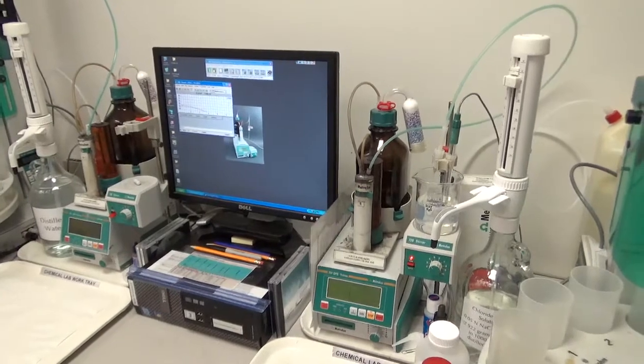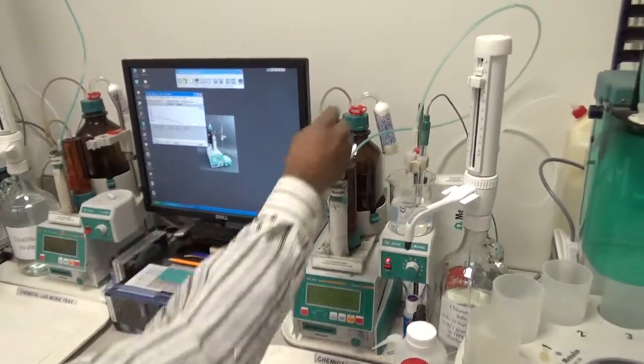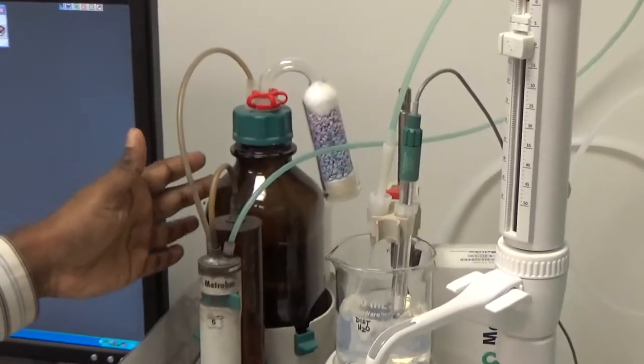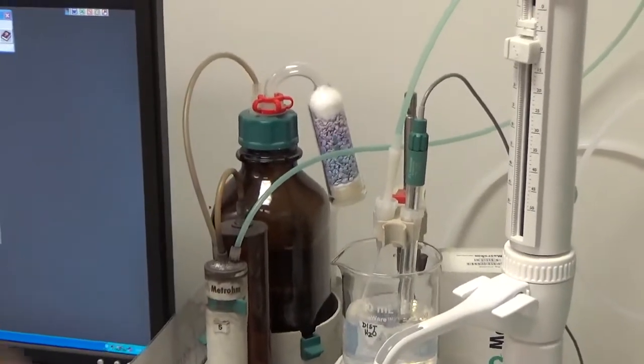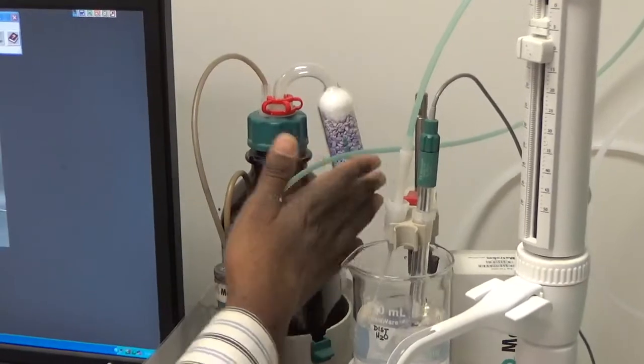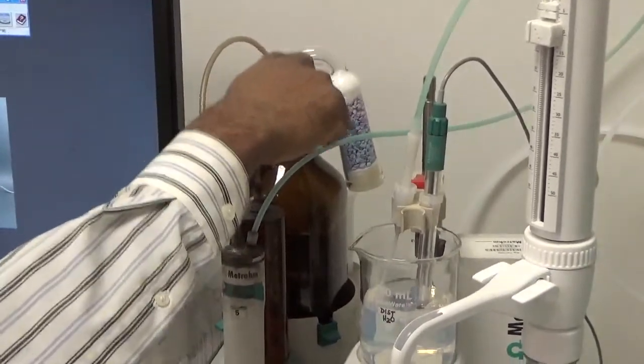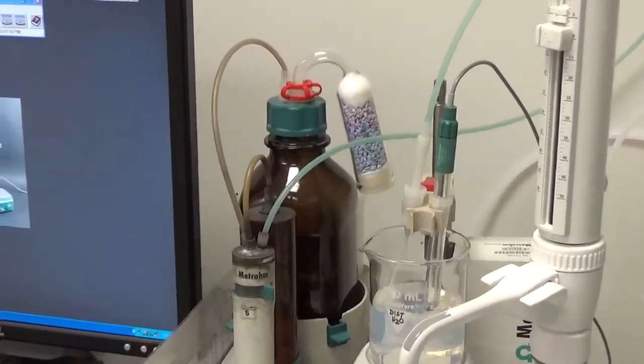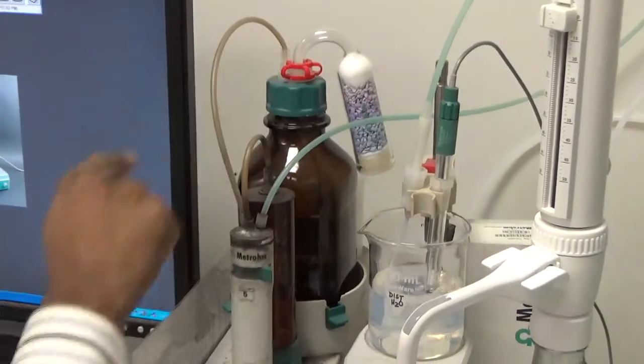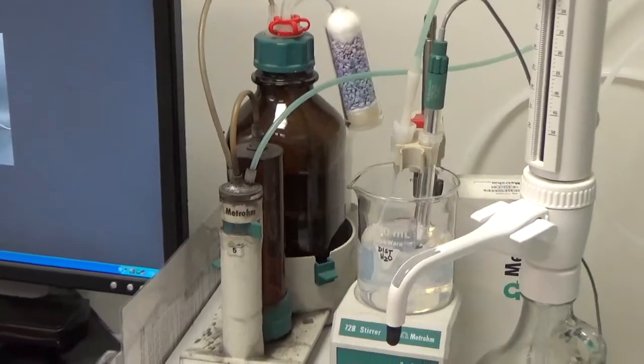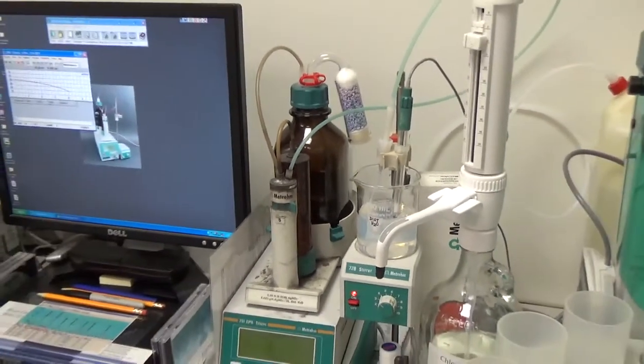Usually we have to use a desiccant to make sure there is no moisture inside the silver nitrate bottle. The desiccant is blue when it is clean, and it turns to pink color when it absorbs moisture. As you can see, it's absorbing the moisture from the bottle, so the blue desiccant is turning into pink. Once it turns completely pink, like this one,